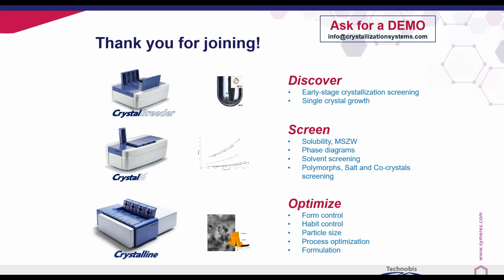When you start to recrystallize in a slurry experiment, please start with amorphous. That is, let's say, the least stable, and it will quickly go into another form, a crystalline form, if it is available. So it's looking at really accessible polymorphs, and hopefully they are stable long enough to identify what your form actually is. So the time point at which you start your analytics, when you isolate your material, is very important when it is aimed for a kinetically accessible form.